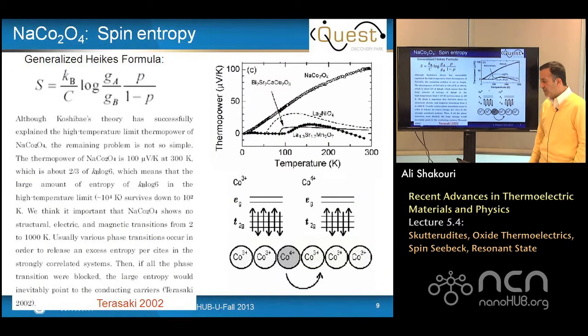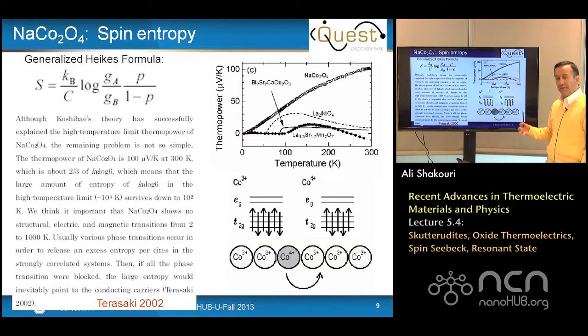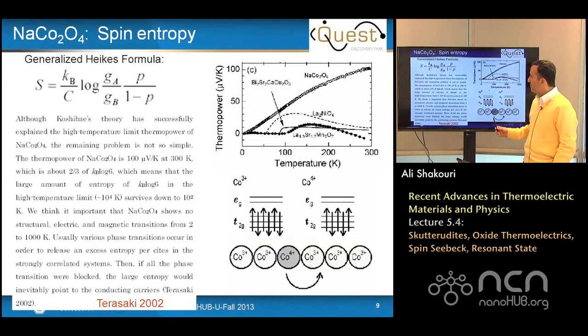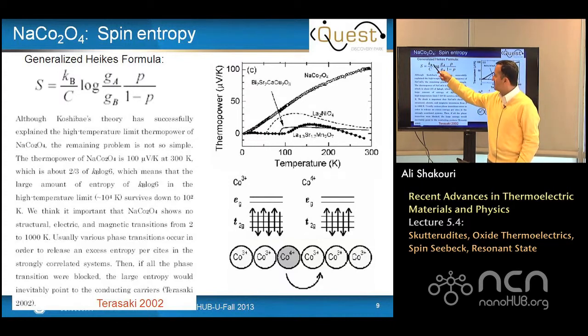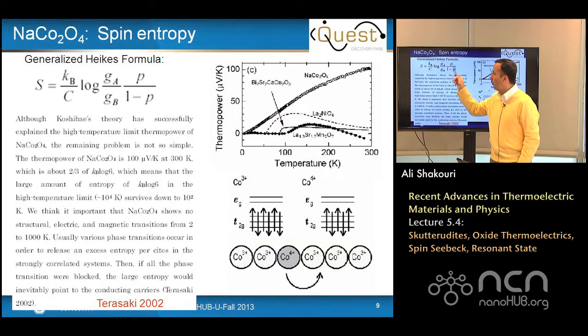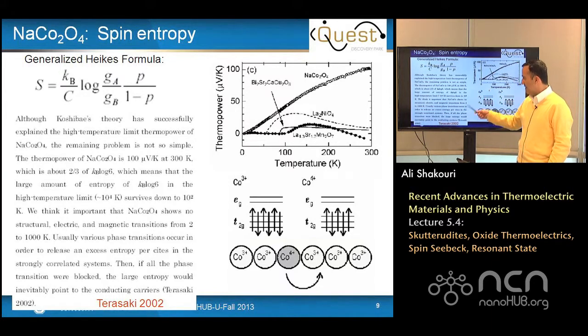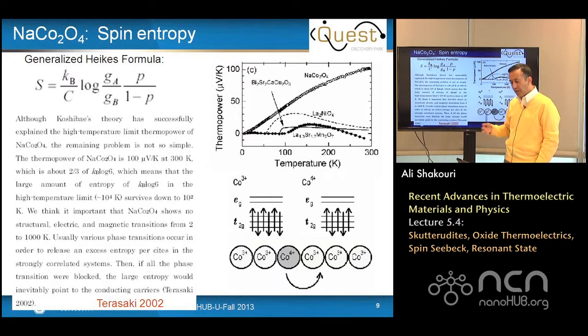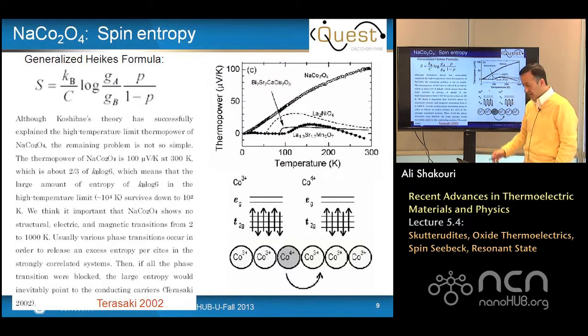The notion of spin entropy: if you have cobalt 3+ and cobalt 4+ states, as electrons move between sites, the degree of degeneracy differs, so electrons carry a certain entropy. This entropy is given by a generalized Heikes formula resembling Shannon entropy, with k_B over charge times a log of the population of filled and empty states with their degeneracy. This explains the very high temperature limit, but it is unclear why a large Seebeck coefficient persists at temperatures significantly below that limit.